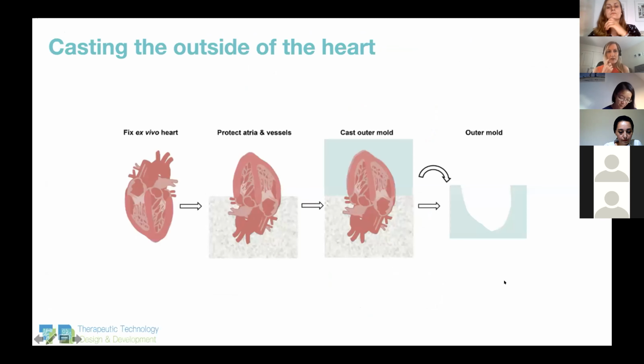So to do that, we had to come up with a lot of different processes to enable us to achieve our end goal. So we took a pig heart ex vivo. It's explanted from the body after the animal was used for another procedure, and we can fix it. There are a lot of different ways we can fix it that will preserve some of the tissue properties, but enable us to use the tissue for much longer without it expiring or getting contaminated. And what we can do then is we embed the atria, or the upper chambers of the heart, and the vessels. We just encase them basically to protect them while we're working on the ventricles at the bottom. And then we can use a cast to cast the shape of the lower ventricles. So we have the outer surface of the heart replicated.